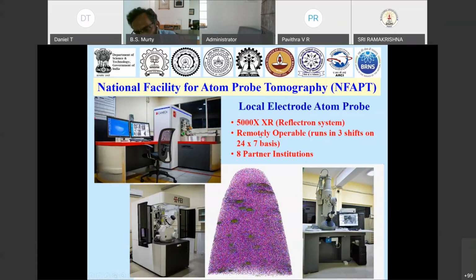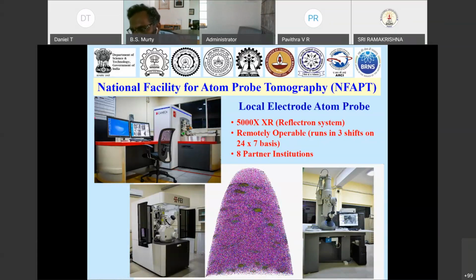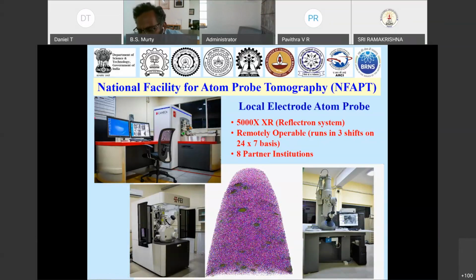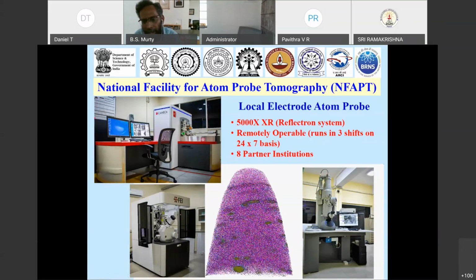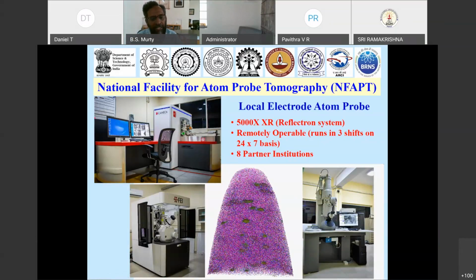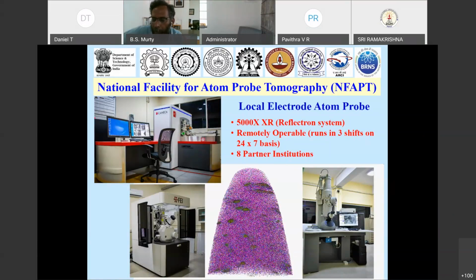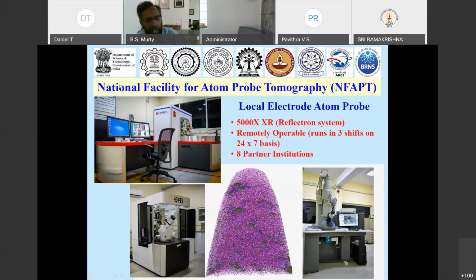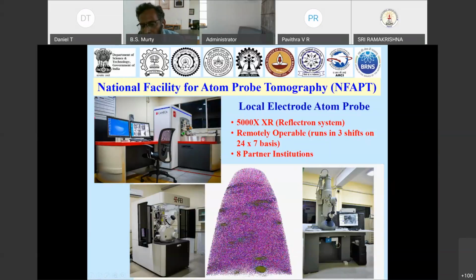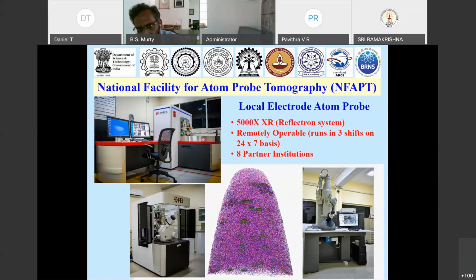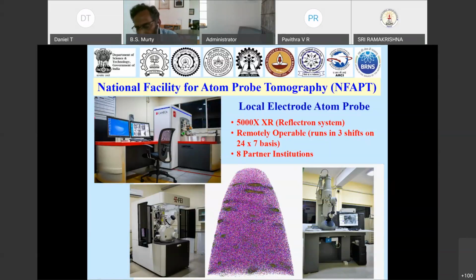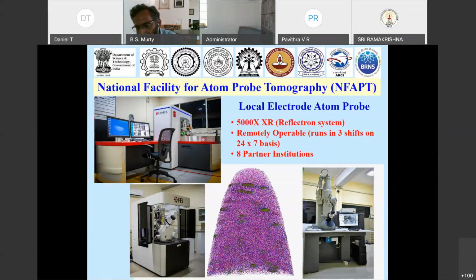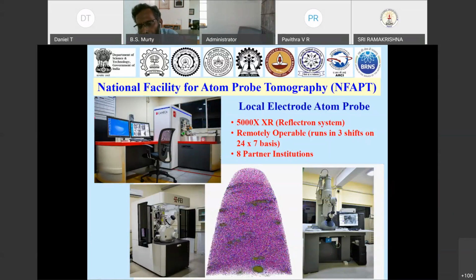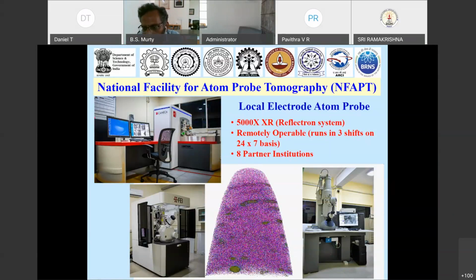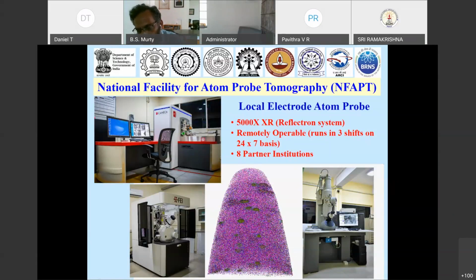What is unique about this is a remotely operable atom probe, where anybody can send us a sample. We polish the sample in a FIB, as seen here, and put it into the atom probe, which is seen on the right and left top. Once you put it in, we get connected to any of these users sitting in various IITs, and they have a small workstation with a connection provided for this, and they can operate the machine sitting at IIT Bombay, IIT Delhi, and so on. That is the beauty of this.